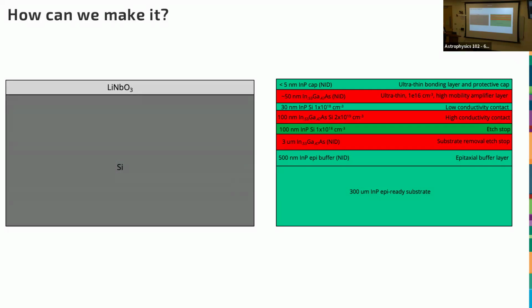We use the technology called MOCVD, if you're familiar with that. Metal organic chemical vapor deposition. There's a couple of Nobel Prizes that were won for it, so you should look it up if you don't know about it. It's very cool. It's a way to basically grow very thick, high purity epitaxial semiconductor things. But the important point is I can grow these stacks of alternating indium phosphide and indium gallium arsenide.